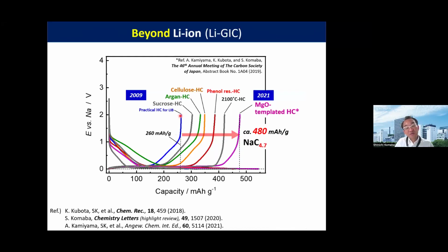Compared to Kuraray's hard carbon and sucrose, argan, cellulose, and phenol resin-derived hard carbons, this templated hard carbon shows extremely high capacity, approaching 500 milliampere hours per gram. So hard carbon shows high reversible capacity.